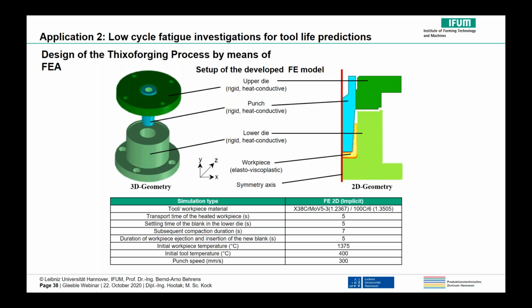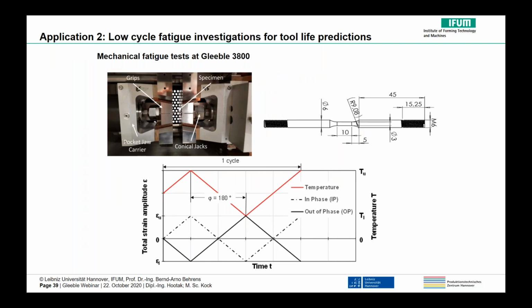But the life model needed to be parameterized. So the so-called low cycle fatigue, LCF, and thermo-mechanical fatigue experiments were performed using the Gleeble system. The process window was determined beforehand by means of FE simulations, taking into account different degrees of deformation, strain rates, and the temperature loads experienced by the tool.